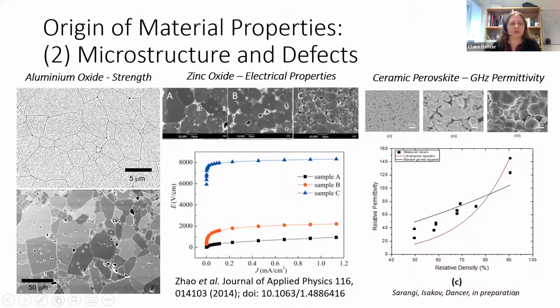So the top one is the sort of thing we want to use if we're going to make something that needs ultra high strength. The bottom one is what you get if you have to compromise on how you make something because you want to make it into a tube so you can use it in the furnace. And what's the difference in the microstructure here? Well, in this one, we're seeing porosity both at the corners, which we do occasionally see in the high purity material, but also within the grains themselves.